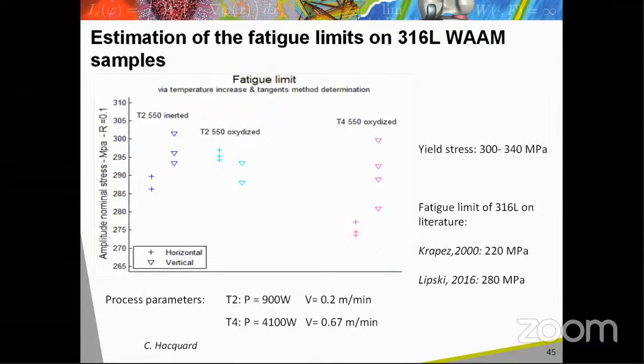Despite a rather large dispersion of the results, one can see that the fatigue limit seems slightly higher on samples manufactured with a lower power. In addition, the fatigue limit seems better in the build direction than the horizontal direction.